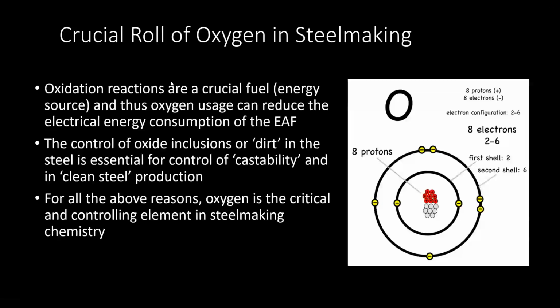So, the crucial role of oxygen in steelmaking: even though we're talking about decarbonization, oxygen is required in steelmaking. The EAF is an oxidizing environment, and we use oxygen for energy, and for controlling dirts, inclusions, and similar impurities. Having silicon in material that ends up in the electric arc furnace, you add oxygen to it, it makes silica, it floats to your slag, and helps you remove those impurities. Basically, oxygen is extremely important to the steelmaking process, whether you're looking at a BOF or an EAF—both methods of production require oxygen.